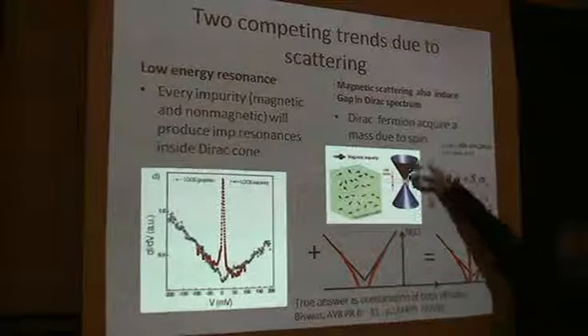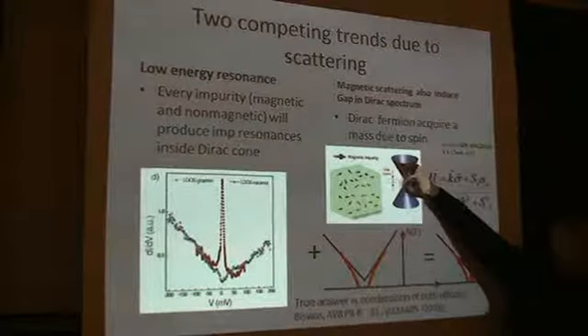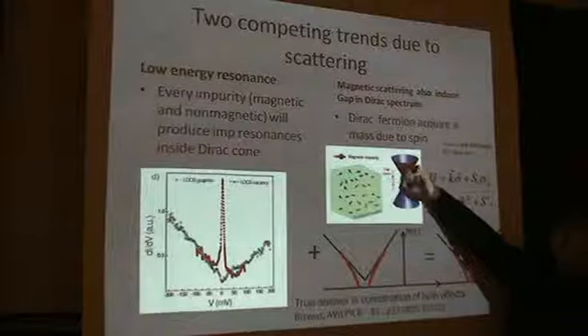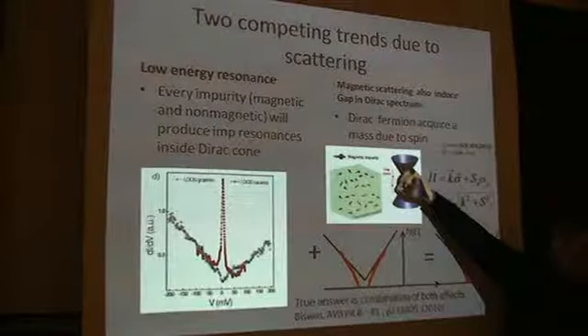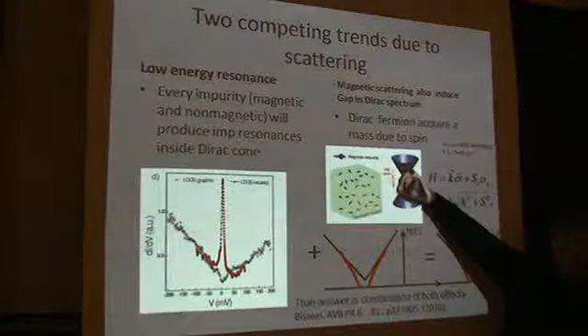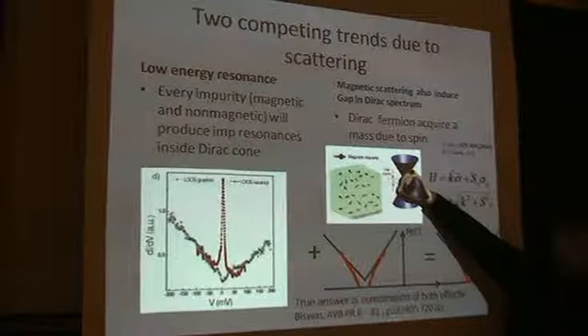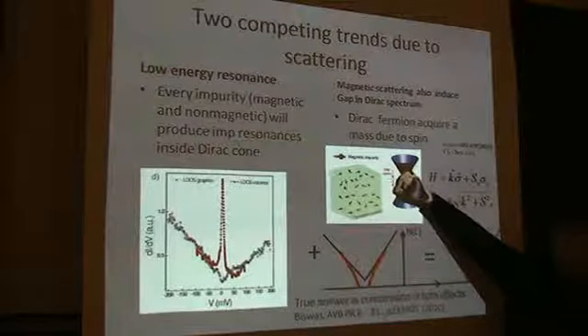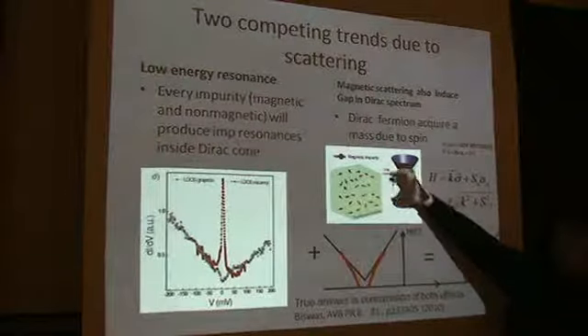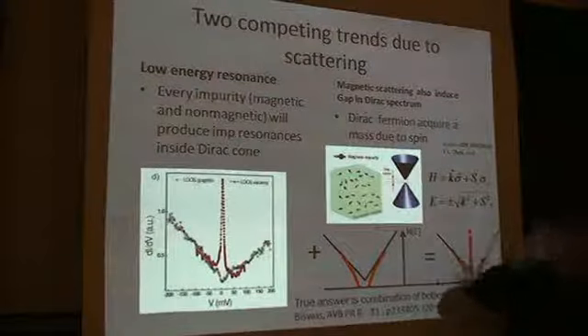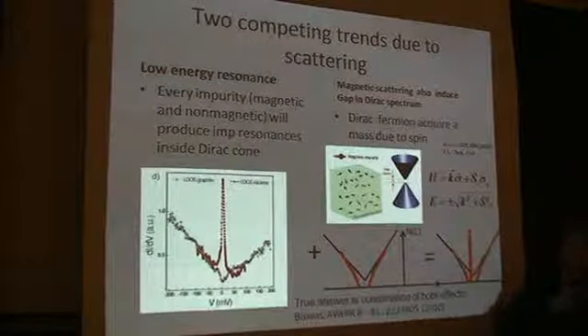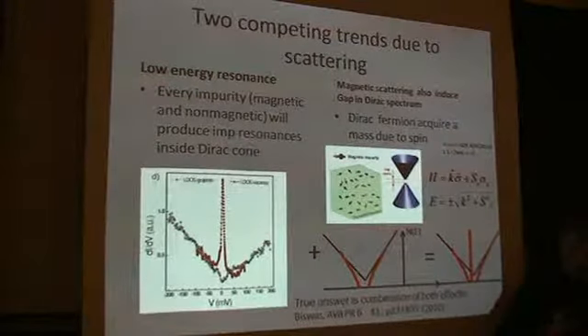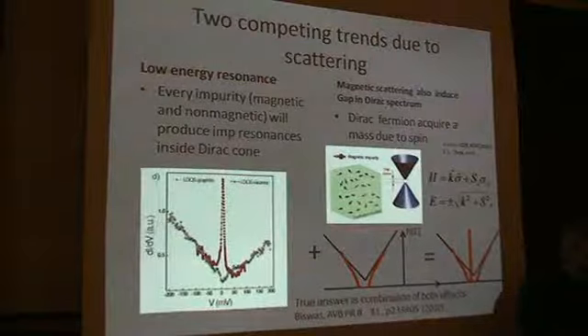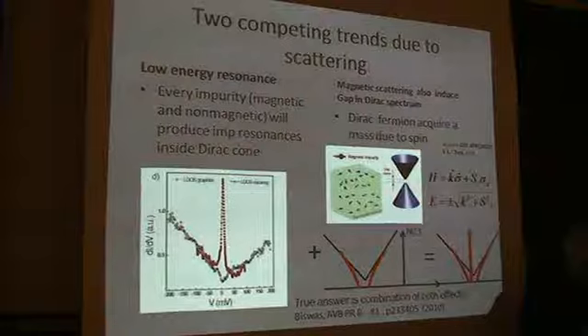I agree with you that there could be some additional interactions. The protection, at least, is coming from the fact that if you have a shrinking phase space, you don't have this Kondo log, or you don't have a BCS log. And so you need to have a coupling that's bigger than the critical one to open up the gap. So I'm saying, like I said, there is always a hammer big enough to destroy it. There is no such thing as unconditional protection. So if you want to open up the gap by turning on the interaction, certainly there is an interaction big enough to do it.